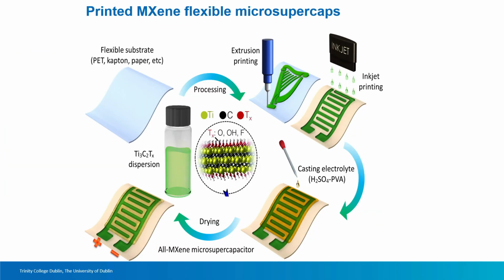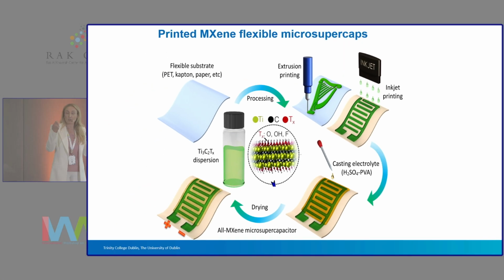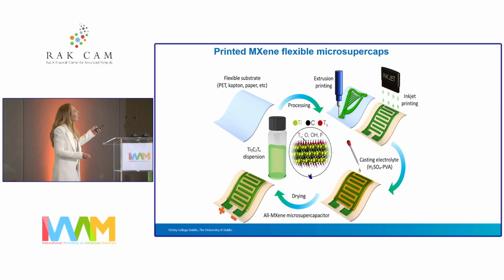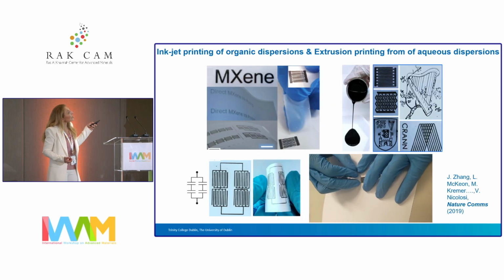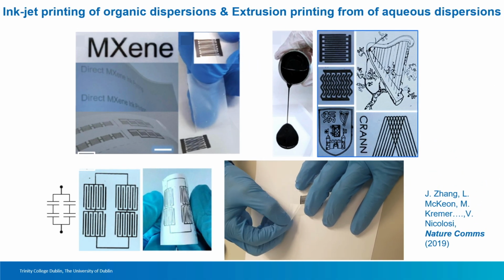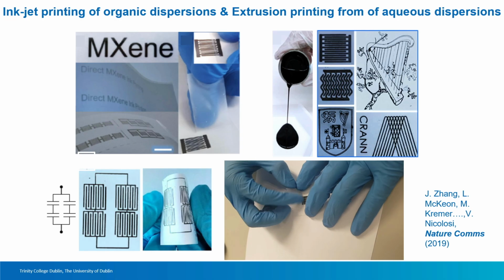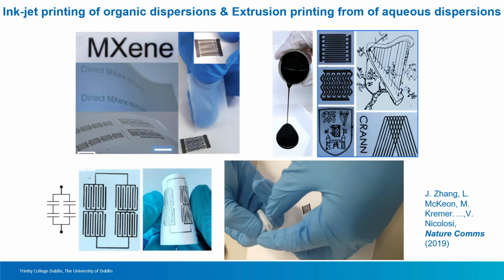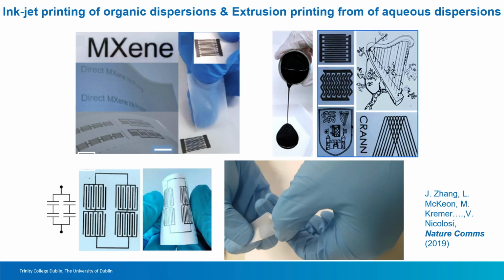Having inks also allows us to explore inkjet printing capabilities. This is the nice thing of having inks in solvents that we control. We can control the rheology. So what we developed are both extrusion printing methodologies and inkjet printing technologies, depending really on the type of solvent and the type of rheology that you have. And we use those to produce all-MXene supercapacitors. So these are just some examples of MXene devices in series, in parallel, all with interdigitated geometry. These are printed on plastic, and these are from water, while these are from organic solvents, NMP.